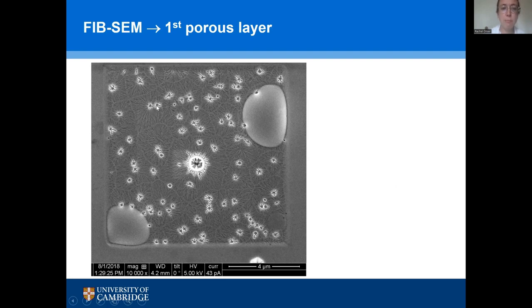But we've got these pipelines, which are the ones we associate with the dislocations. We see the porosity emanating from them, and we see these same borders that we've noticed between porous domains before.